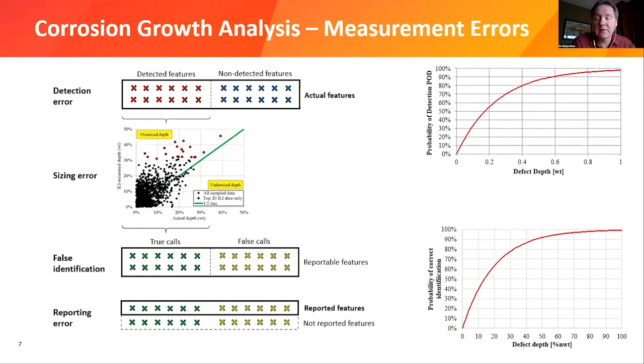And then we have one due to inspection errors or measurement errors. And there we have several types that are some sort of already built in that list of defects that we obtain from the ILI vendor. We can have detection errors. So out of all the defects in a pipeline, not all of them are detected. And to describe what is happening probabilistically, we use a so-called POD, probability of detection curve. As a defect is large, then the probability of detection is very high. So there's a high chance we will actually capture those. Usually POD is very low when it comes to defects that are very small. That's relatively good for us because the smaller ones, we are not as worried from an integrity perspective. But we have to keep in mind the list of defects that we have is not complete. We're still missing some that are not included.